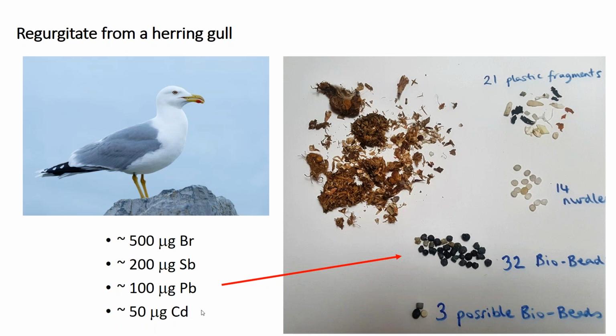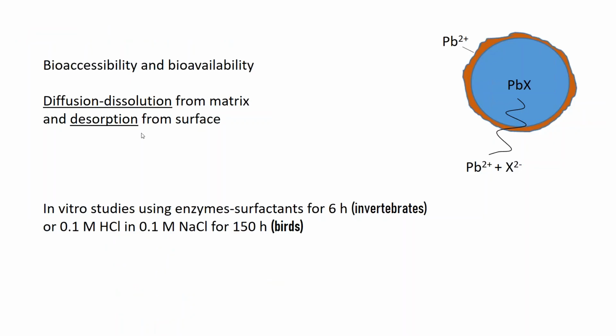And of course, the question is, is it available to the bird? Is it accessible? Well, if we think about the plastic, let's say a pellet or a biobead, we have something like lead as an additive inside, and we have lead which is adsorbed on the outside, at a much lower concentration here. The question is, how easy is it to extract something like lead from this coating, this fouled film, and how easy is it to extract the lead diffusing out of the plastic matrix? So there are two processes, desorption really and diffusion.